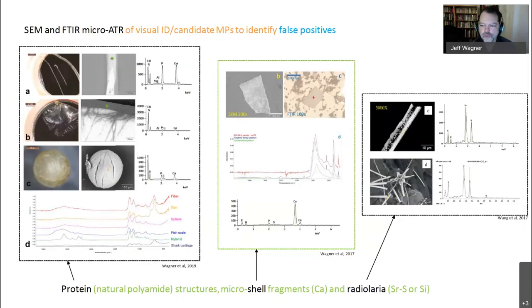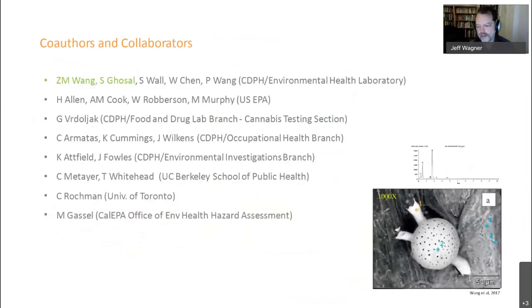And then finally on the right, you see fibers, which under the SEM are clearly not microplastic fibers, but rather zooplankton, radiolaria, often silicon-based, but in some cases, such as the ones you're seeing here, belong to organisms which concentrate strontium and sulfur into these strontium sulfate structures. With that, I'll leave you with one more picture of a silica-based